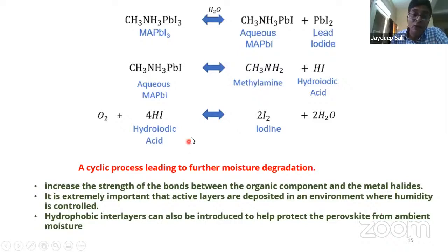So what can we do about this? What are the possible options? Firstly, increase the strength of the bond between the organic component and the metal halide. So you can choose different options for the A and B positions. It is extremely important that active layers be deposited in an environment where humidity is controlled. There are many studies on how humidity during manufacturing is affecting the perovskite.